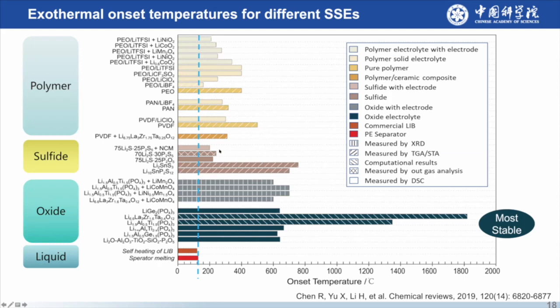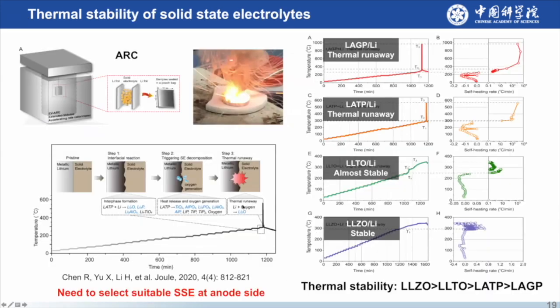And the very important issue is the thermal stability. So we have considered and compared the thermal stability of the different solid state electrolyte. With this summary, you can see all kinds of solid electrolyte have much higher thermal stability compared to the liquid one. This is very good news, at least, although it's well known. However, it looks like the oxide electrolyte is most stable, then sulfide, then polymer. But what's the real case? So you need to do the experiment.